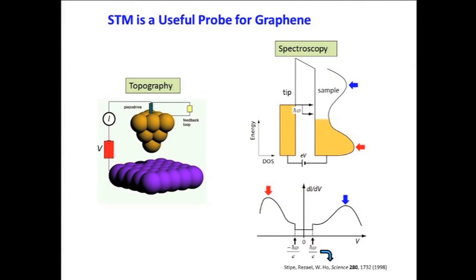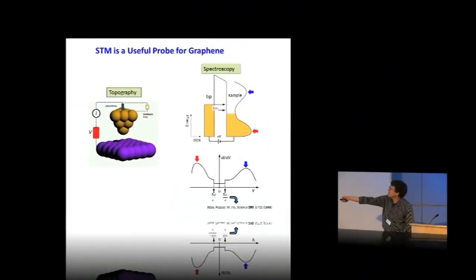And this is a very useful quantitative measure because the electronic local density of states gives you a measure of the probability of finding an electron at a certain point in space at a certain point in energy. So if you can map that quantity out, you can learn a lot about what the electrons are doing in small structures. Also, by varying this voltage and measuring the differential conductivity of this STM tunnel junction, you can measure what we refer to as dI/dV.